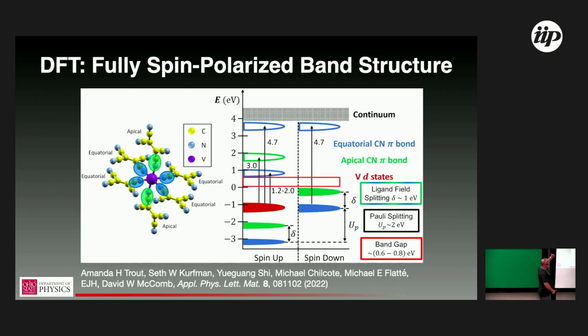If you think about the stoichiometry of vanadium TCNE2, what that means is that not all of these terminal cyano groups, so I should have explicitly said this, the yellow here are carbon, the grays are nitrogen. It's the nitrogen that are directly bonding to the vanadium, which is a pretty strong metal bond. But not all of these terminal cyano groups get a vanadium. Every vanadium is fully coordinated, but not every TCNE is fully coordinated.